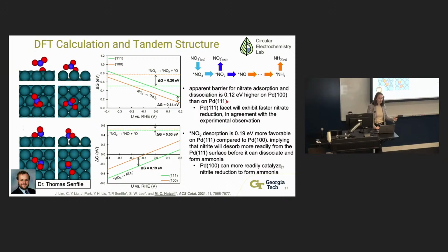And that's what we thought from our experiments, but it was good to confirm through theory that it was able to adsorb nitrate, which decreased the barrier for nitrate to get to the surface. And then he also found that nitrite desorption was almost 0.2 eV more favorable on the 111 surface when compared to palladium 100. Again, a potential indicator of why we saw better nitrate reduction. I will note that 0.1 and 0.2 eV are, from a catalysis perspective, significant in improving the catalytic activity. So by improving something by 0.2 eV, that does help.